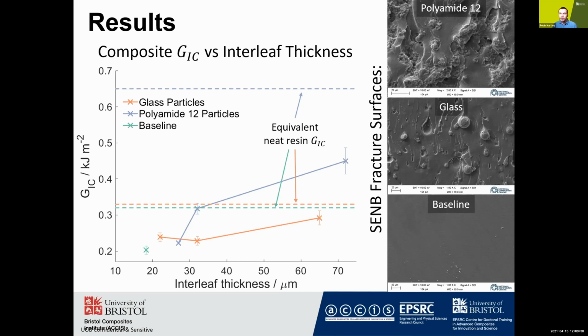The other thing to note is that although the mode 1 G1C values increase with interleaf thickness, they never actually match the values achieved in the resin tests, and this is true at all interleaf thicknesses tested in this study. This is because the full development of the crack tip plastic zone is constrained by the adjacent fiber layers.